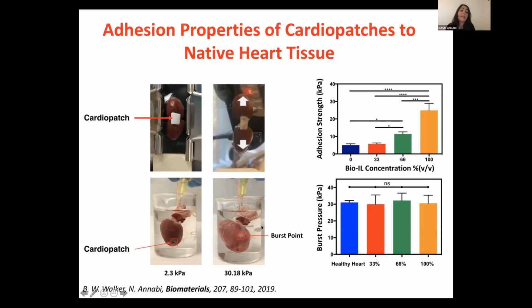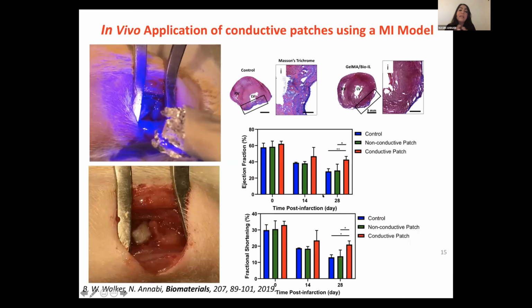In the bottom panel, you see the burst pressure test. This is whole rat heart. And then we show that the patches can adhere to the heart. So when you apply it, you do not even need to suture it to make it stable on the heart. So here are some preliminary data that we did.